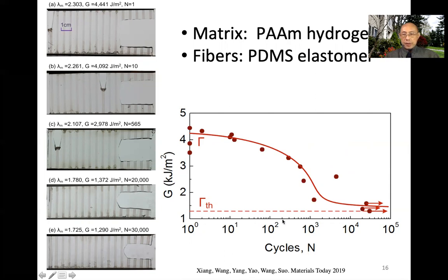So here's a fiber and a matrix, and we tested it under cyclic loading, looking at the number of cycles against the applied load. As the load becomes smaller and smaller, the number of cycles you can apply without causing any damage increases. So this is 30,000 cycles. You still have no damage. So keep cycling, no damage. This G is already beyond 1,000 joules per meter squared. So this is a unit of kilojoules per meter squared. So that's the threshold. That's a new value of the threshold.